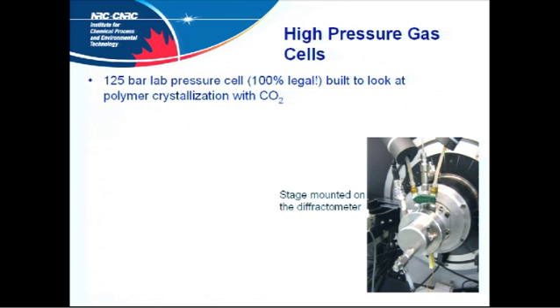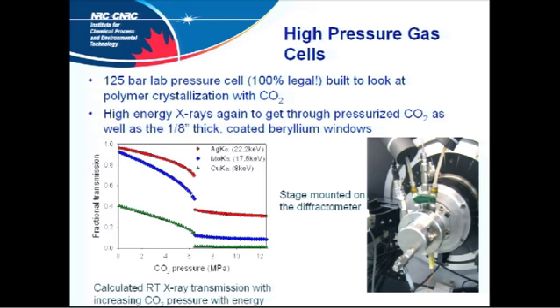You know, built to look at polymer crystallization with high pressure CO2, which goes supercritical, so you effectively get the density of water. So you've actually got to punch through quite a lot of material here, both the sectional windows to actually hold the pressure, and the actual material on the inside.